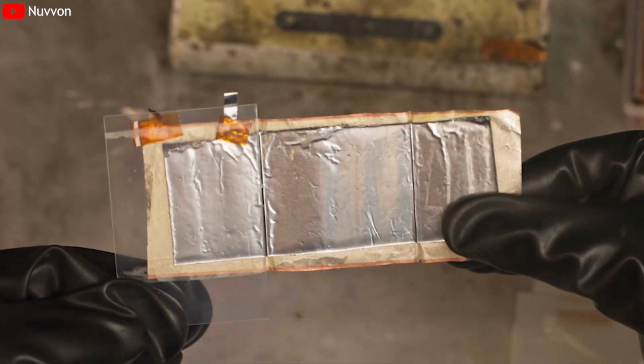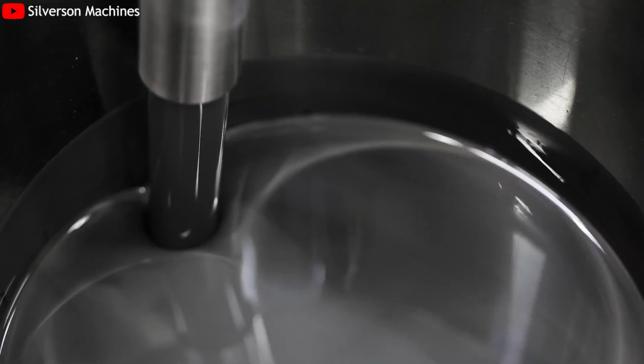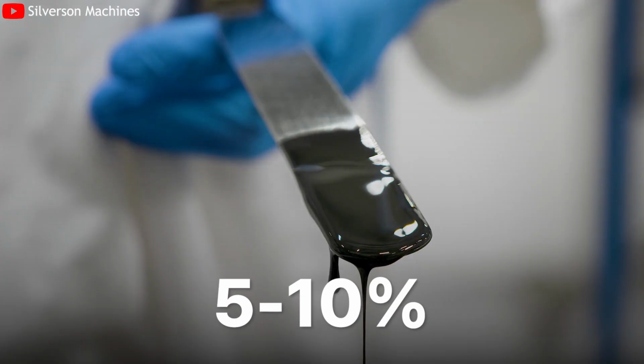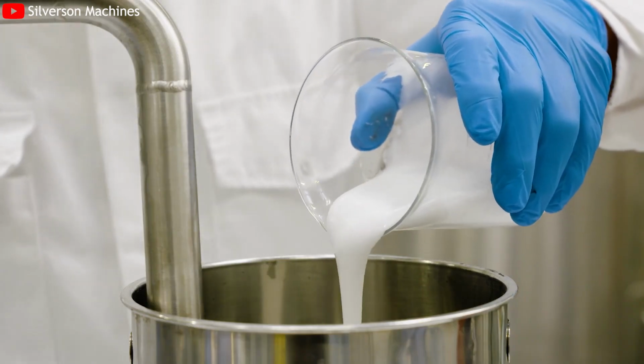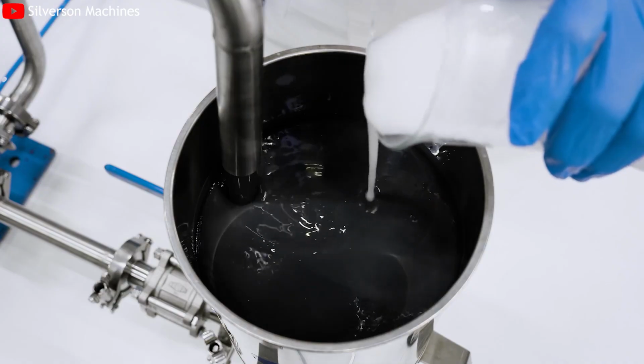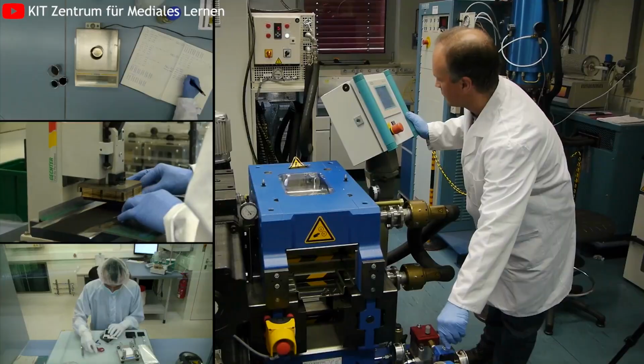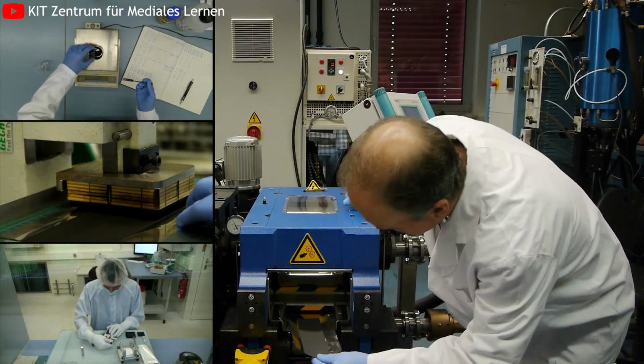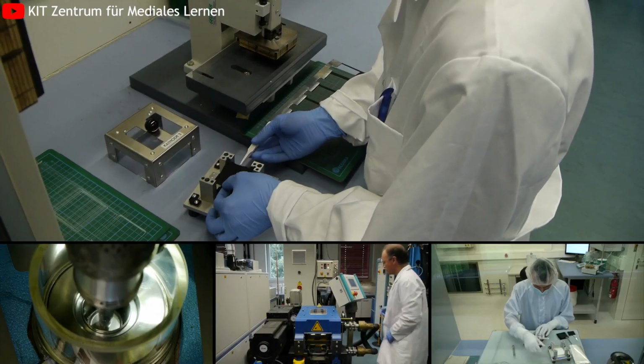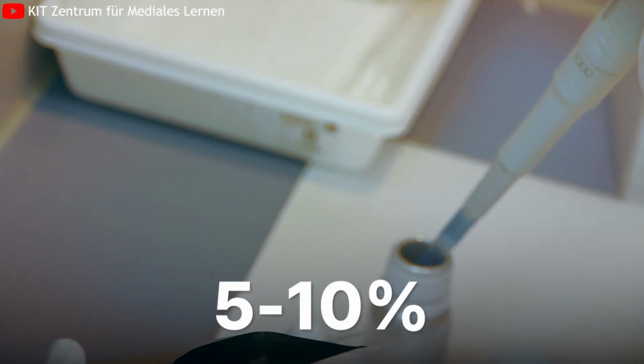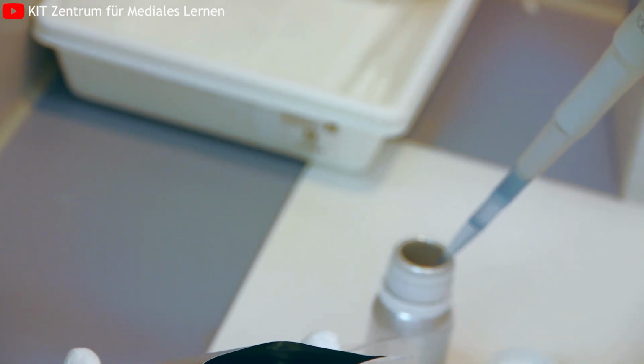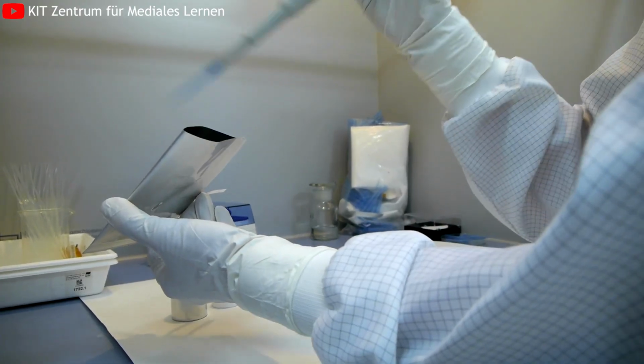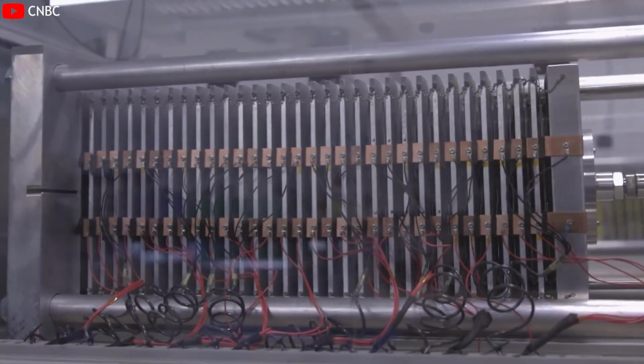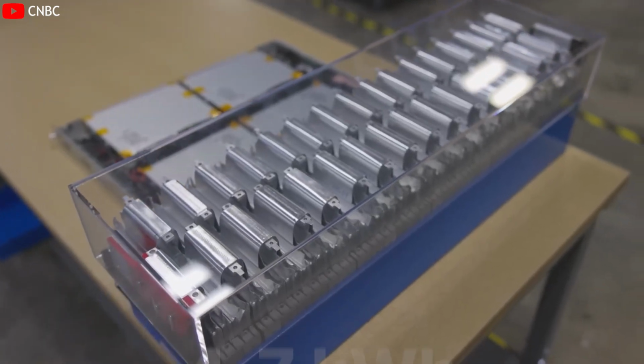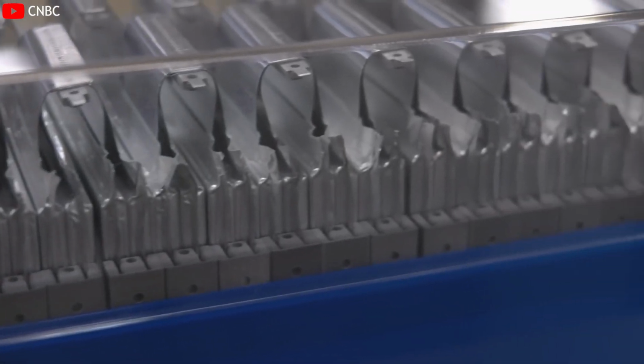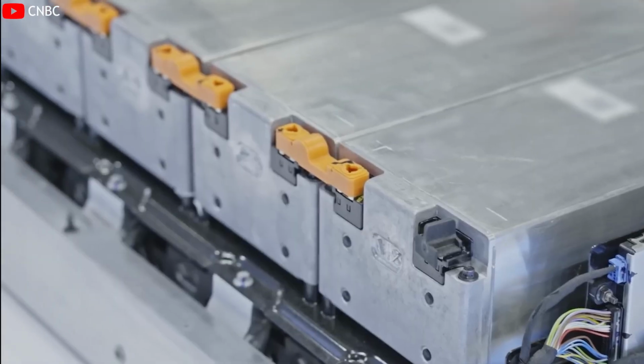Energy density improvements follow directly from binder reduction. Conventional wet electrodes typically require 5 to 10% binder by mass to maintain mechanical integrity after solvent evaporation. Tesla's dry electrode process reportedly operates at roughly 1.25% binder content. That freed mass is replaced by active material, enabling a 5 to 10% increase in cell-level energy density without altering the underlying electrochemistry. In a 75 kilowatt-hour battery pack, that improvement equates to an additional 4 to 7 kilowatt-hours of usable energy, or a 20 to 30 kilogram reduction in pack mass.